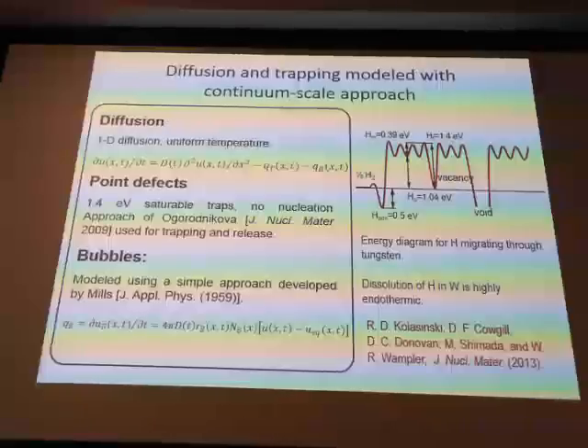So we considered the energetics of hydrogen being transported through the surface using a simple 1D diffusion model. We assumed uniform temperature within the sample, and we're basically treating the concentration of the hydrogen within the material, and then the flow within the traps, and then into the bubbles themselves. And then we treated the point defects as saturable traps, assuming that the deuterium would not nucleate any of these defects. And then we looked at the flow of the hydrogen through the material and into the bubbles themselves.